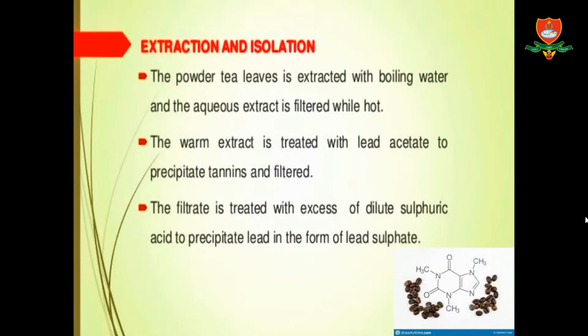The powdered tea leaves are extracted with boiling water and the aqueous extract is filtered while hot. This warm extract is now treated with lead acetate to precipitate tannins and filtered. This filtrate is now treated with an excess of dilute sulfuric acid to precipitate lead in the form of lead sulfate. So next slide, ma'am.